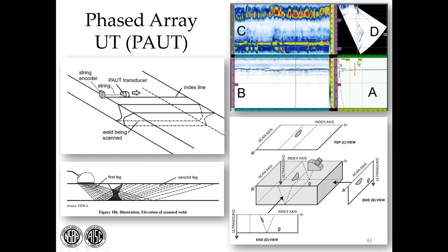on this particular view. Then if you look at this diagram, and this diagram is out of the code, it tells you how each of these views is oriented to the weld. So the C view is looking down on top of the weld. The B view is looking at it on this axis. The D is looking at it from the end. And then the A is not a particular orientation, but rather it measures the spike.